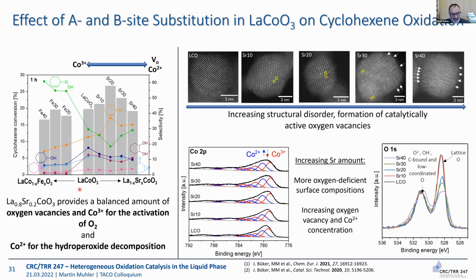Now we make use of the perovskites. In the perovskites, you can substitute the B position with iron, but then you see the conversion, the gray bars, doesn't increase, actually it decreases. But you can also substitute lanthanum 3+ by strontium 2+. That means you have to compensate for the missing positive charge. And this can be done either by forming cobalt 2+ or by oxygen vacancies or by both.